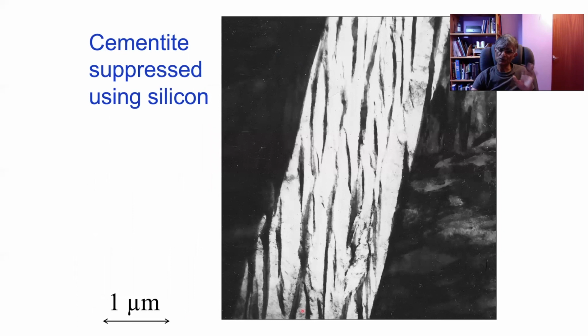And I showed you this microstructure, which is beautiful with these fine platelets of bainitic ferrite and retained austenite in between. But this is not a nanostructure. Each of these plates is about 1/4 of a micrometer in size, and it's transformed at around 400 degrees centigrade. So we need to suppress that transformation temperature.